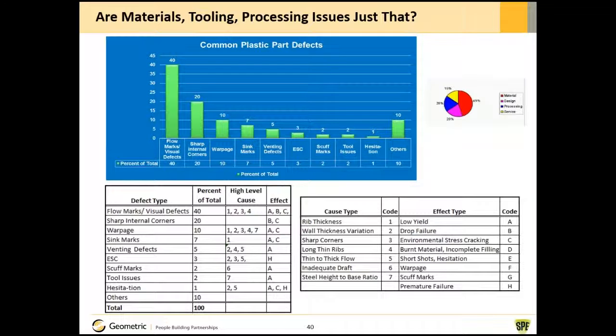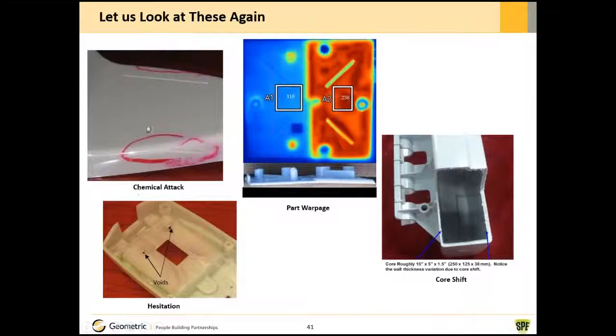Let's look at these again. Chemical attack, poor choice of material? No. There was a sharp corner here and it causes a very high stress concentration. That's why it failed. It could have been controlled by better processing, higher melt temperature, higher melt speed, higher mold temperature. No. You caused the problem by surrounding a thin area by a thick area.